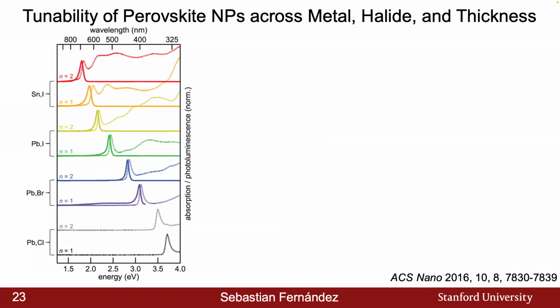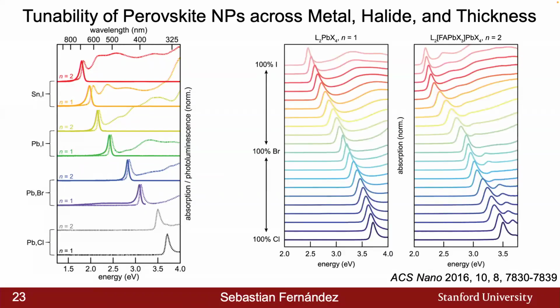And lastly, across thickness, and perhaps one that I'll take some time to briefly explain, is that for any one of these metal halide pairs, if we compare the n=2 to the n=1 case, the n=1 is always at a much higher energy and is more blue shifted than n=2. And this should make sense from quantum mechanics. We know that quantum confinement effects will increase the optical band gap of these materials. And so for every one of these cases, the thinner nanoplatelet will have a higher emission. The authors also looked at mixed halides, and we can see these beautiful transitions in the absorption spectrum for both n=1 and n=2 nanoplatelets.